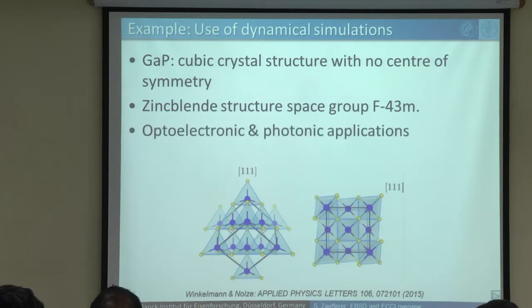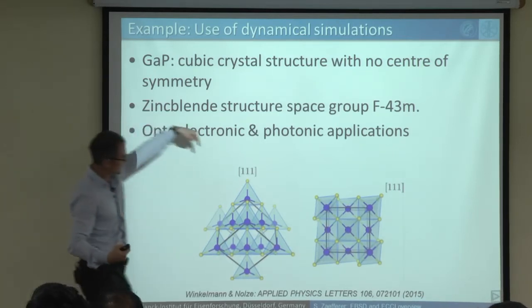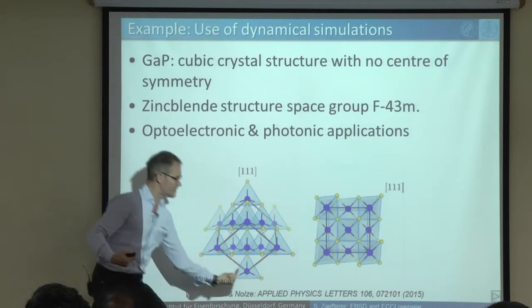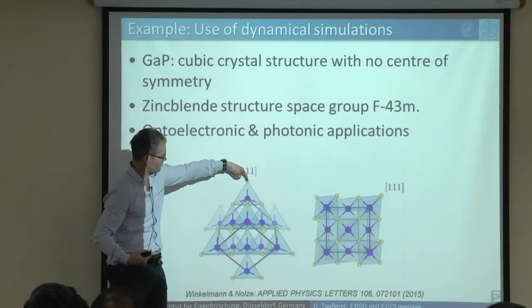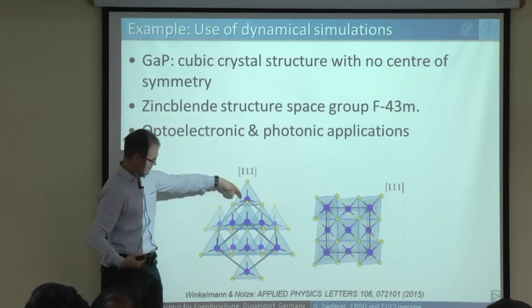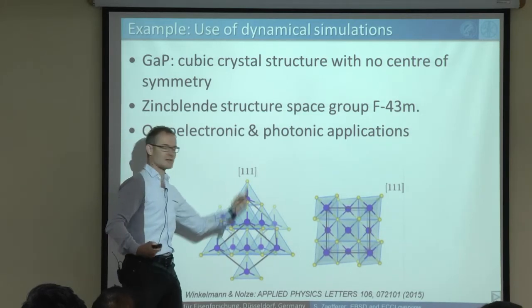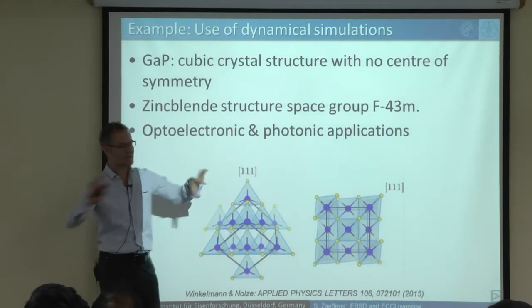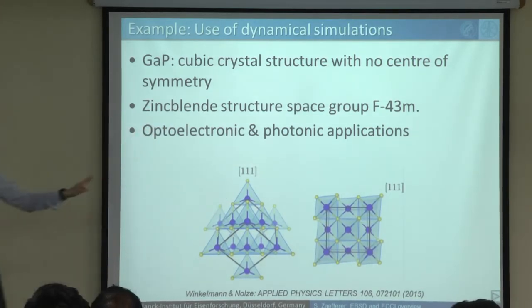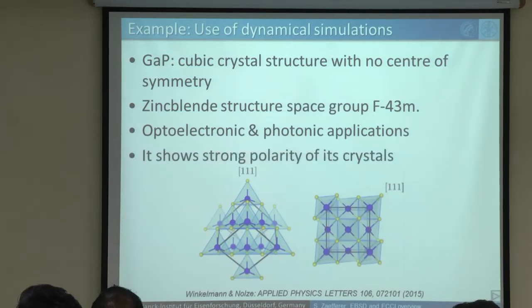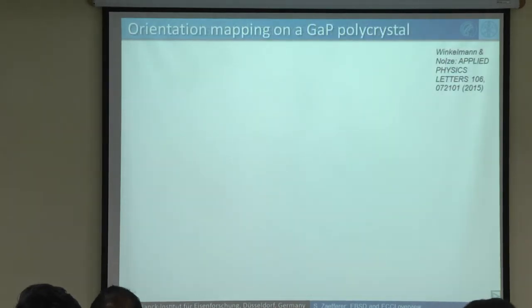Okay, and the material has important applications for optoelectronics, and for these applications it's very important whether you are looking in this one direction or in this direction, whether you first hit a phosphorus and then a gallium, or whether you first hit the gallium and then the phosphorus. This influences the optoelectronics very significantly. So is EBSD able to separate whether we have 111 or minus 111? And that is shown here.